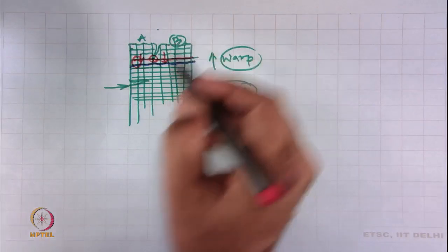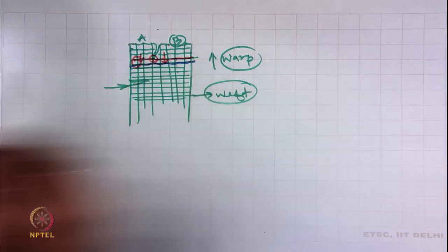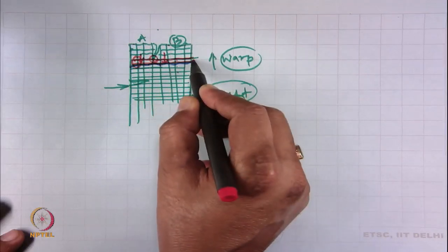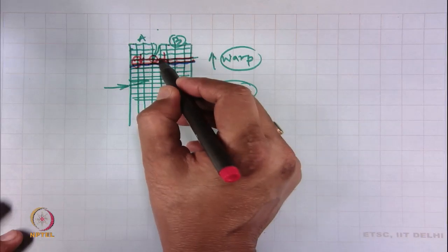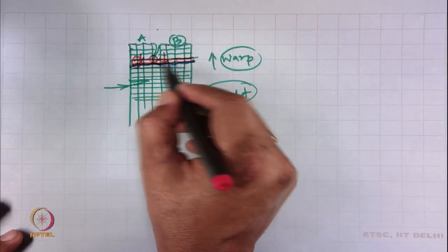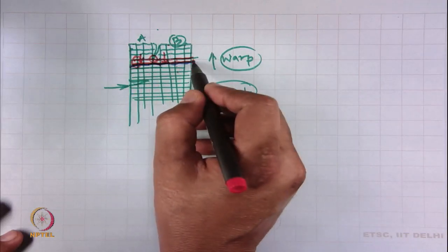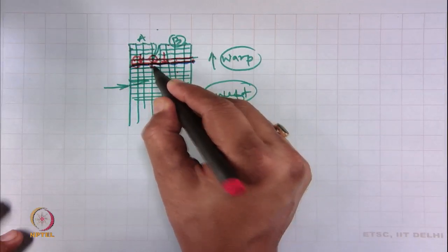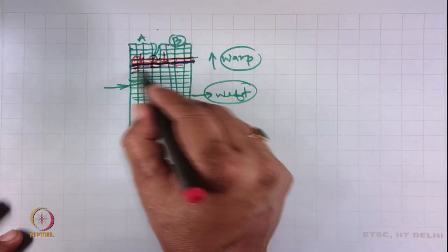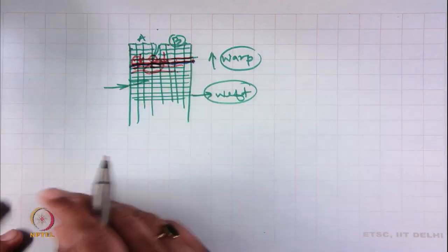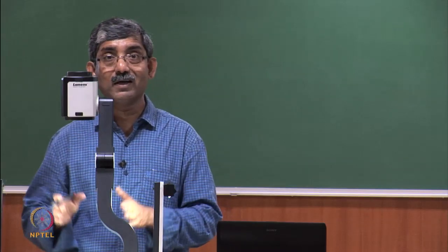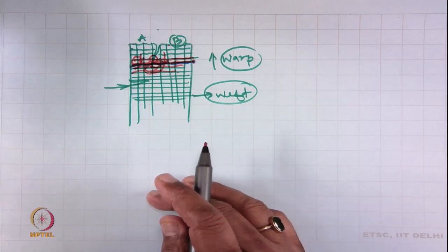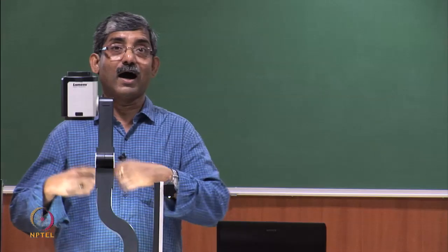If these yarns are sliding, this red yarn will actually come close to the blue yarn. The red will not break, but has slid close to the blue yarn. So, they have formed a double yarn, and this double yarn will again slide to a third yarn, and in that way they will form a group of threads before they break. This is due to the sliding and grouping of the threads, and ultimately we will see the tear strength becoming higher and higher.